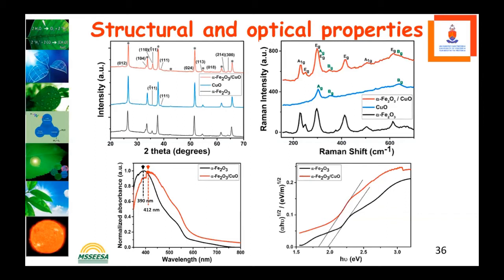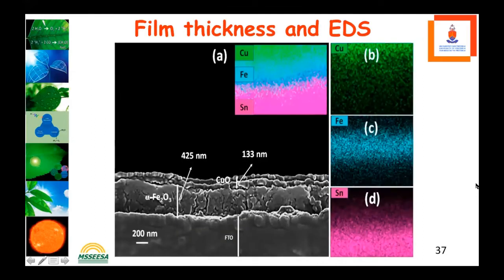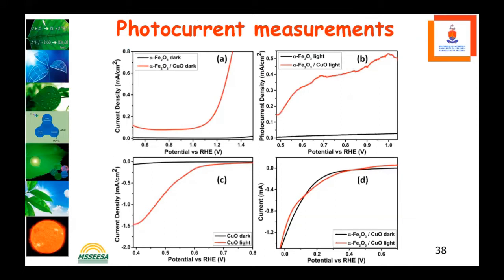So if you look at the hematite alone and the heterostructure, you find that the absorbance is not really changing that much, but you can see that the heterostructure is improved a bit. And then the band gap of the heterostructure is a bit less than the band gap of hematite alone. Let me skip this slide and go to the photocurrent measurements.